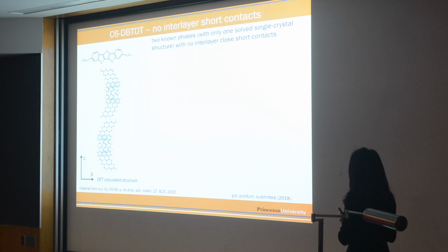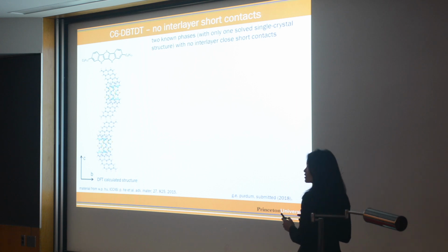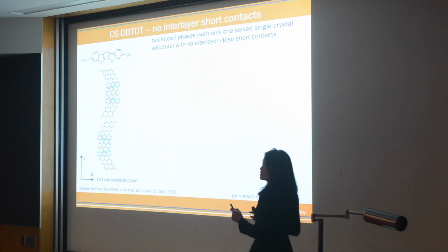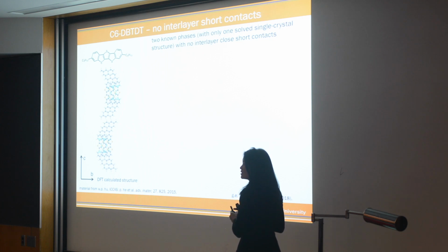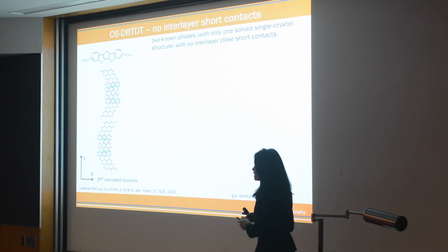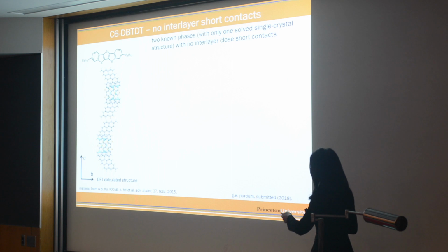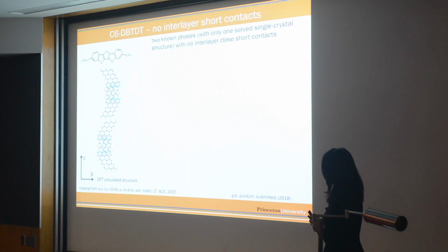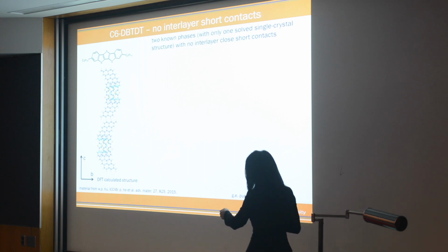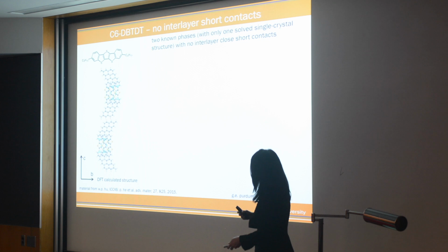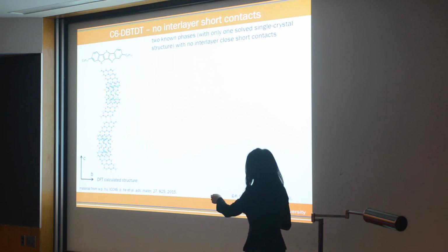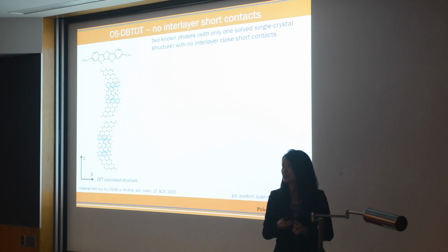So this is DBTDT. It's got two known phases, only one solved crystal structure. And unfortunately, the crystal structure that we access is not the solved crystal structure. And so our collaborator actually did some DFT calculations. So this is a crystal structure that's gotten from DFT calculation. And again, you can see that these are the conjugated core, and there are short contacts between the conjugated cores. That's to be expected. They form a layered structure with no short contacts between the layers.